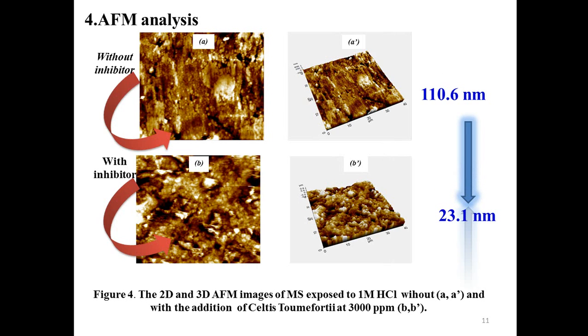Detailed AFM analysis was carried out to obtain the average roughness factor Ra. The average Ra in uninhibited 1 molar HCl was found to be 110 nanometers. The addition of 3000 ppm to the aggressive solution reduces the Ra to 23 nanometers. The reduction in Ra can be assigned to the formation of an organic film on the surface, which has a compact structure and covers pits well.